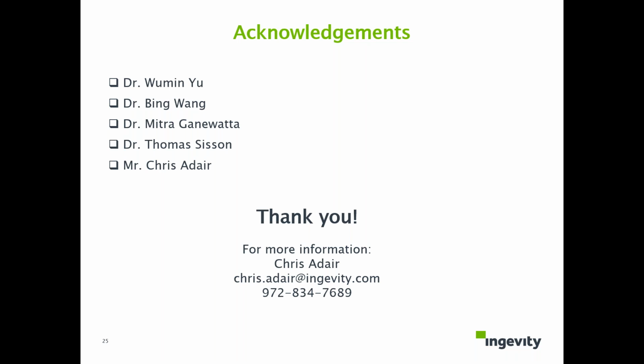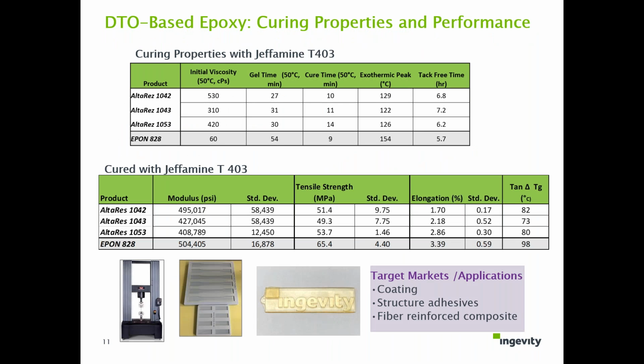And in slide 11, is the cure time and gel time reversed? Typically, the gel time is shorter than the cure time. Good question. By definition, because I have worked in the composite area a long time, if people call it the total time, it is definitely longer, because gel time plus cure time equals the total time. For the definition in this table, we call the cure time the time starting when they reach gel, when it starts the timer. When they reach the peak, we stop the timer. This is the number we put here to count cure time. So most people report what should be called the total time, which is gel time plus cure time. If you see it this way, it will definitely be longer than gel time.